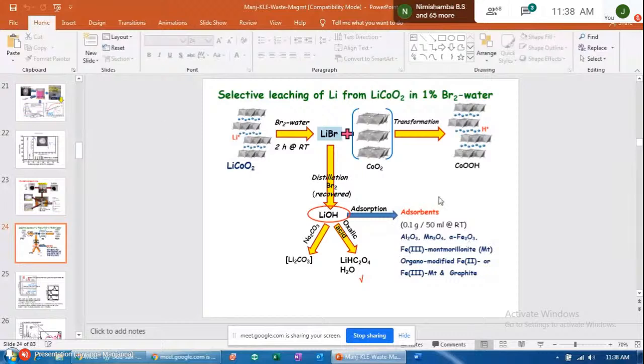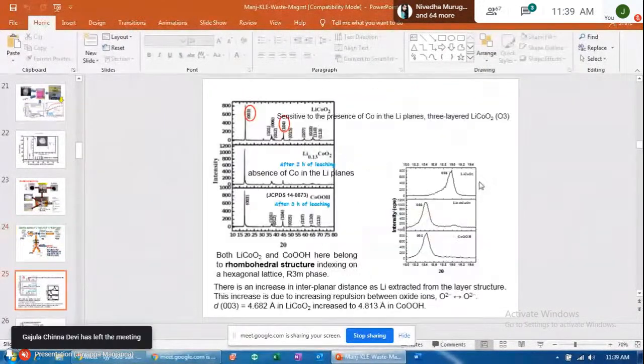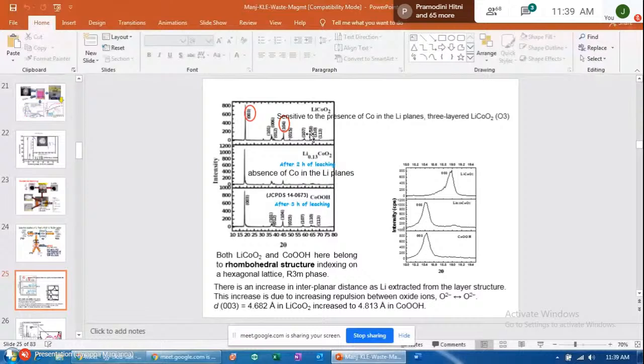Okay, that's how we do it, and we also take out some of the lithium by adsorption on different materials. This is how you can do a lithium depletion, 100% lithium depletion from this lattice. When we studied all this, we looked at X-ray diffraction to see how the lithium is removed over different times. Partial removal to complete removal of lithium was monitored.